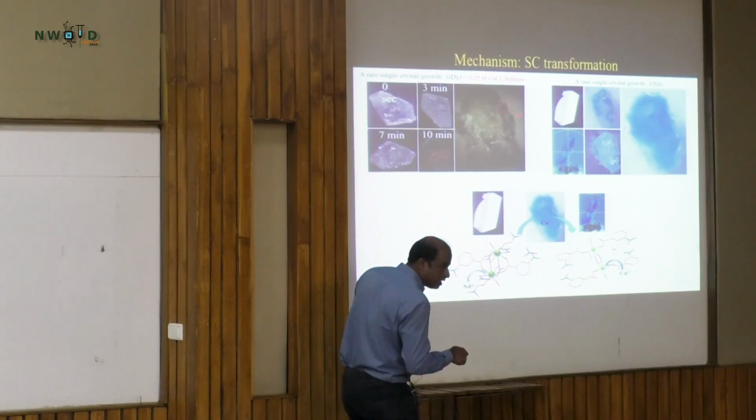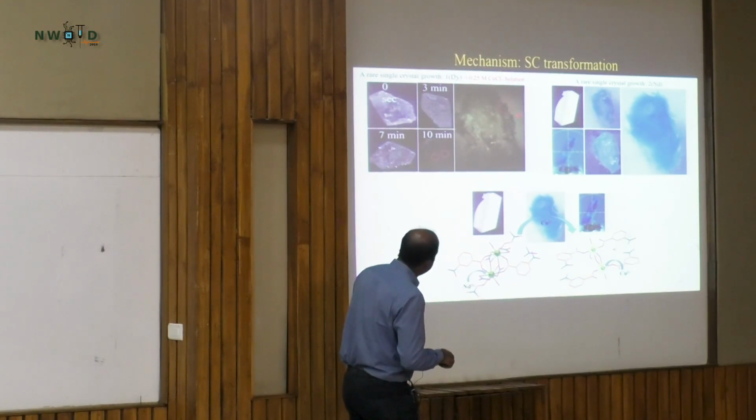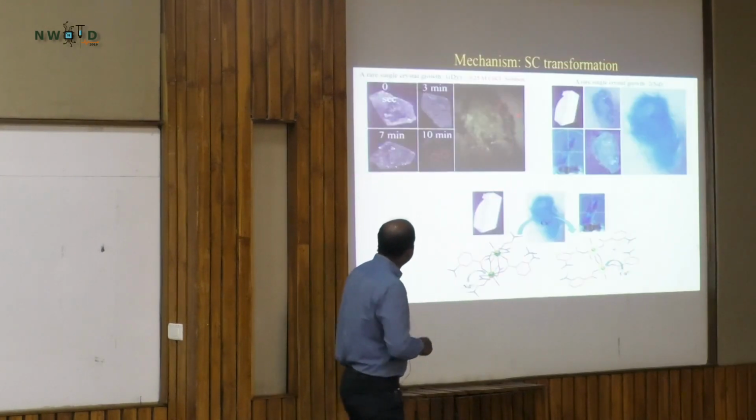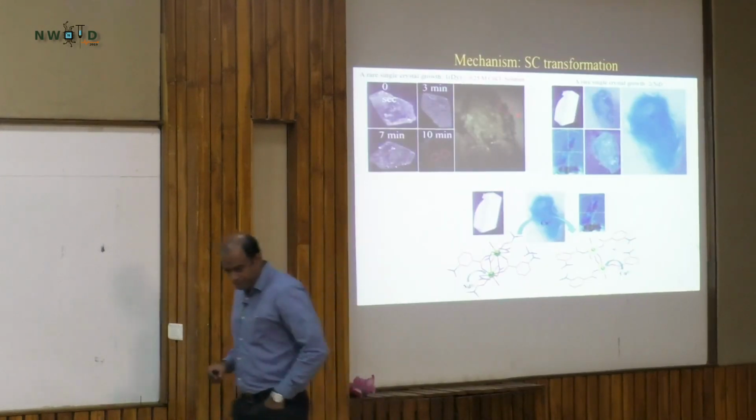And one needle we have taken, and then took the single crystal XRD and refined the structure. And then we see that the structure from here to here is changing from orthorhombic to tetragonal upon copper capturing into the system. So there is a single crystal phase transition happening.